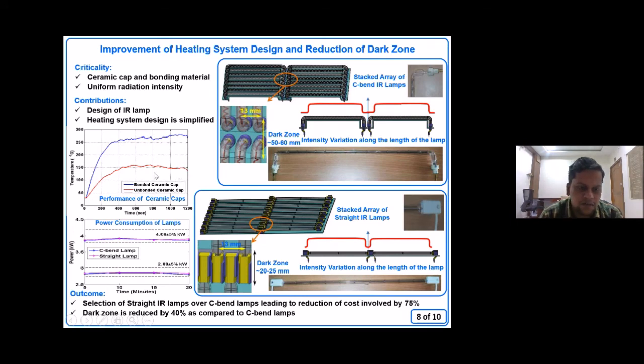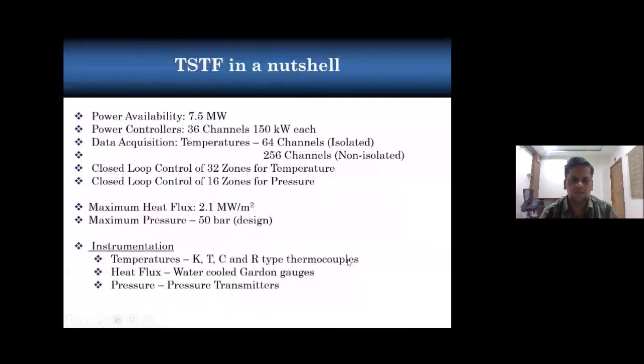So now we have tested for a very long duration, almost 100 seconds we switched it on. Nothing happened in open rack condition, not in assembled condition. In this way we qualified those lamps. The power ratings are also matching. Due to this, we have reduced cost by almost 75% compared to the C-band lamps. The dark zone is also reduced by 40%.